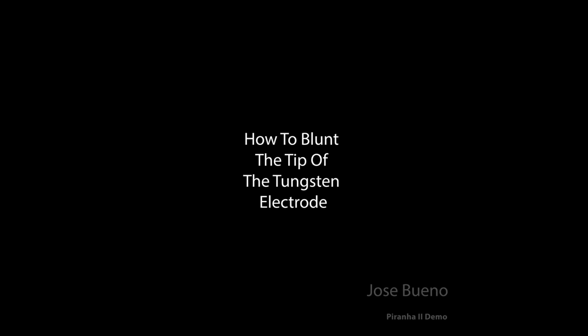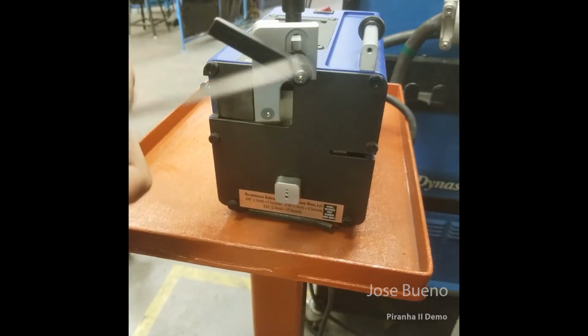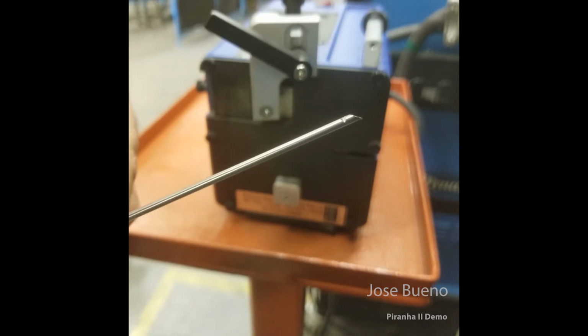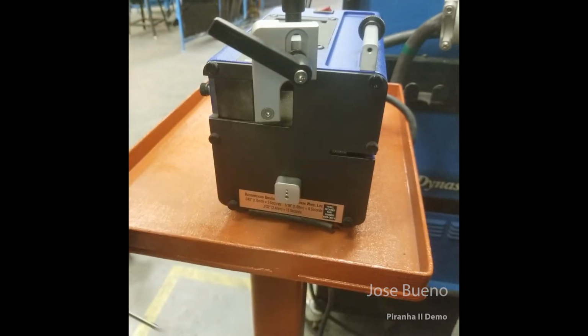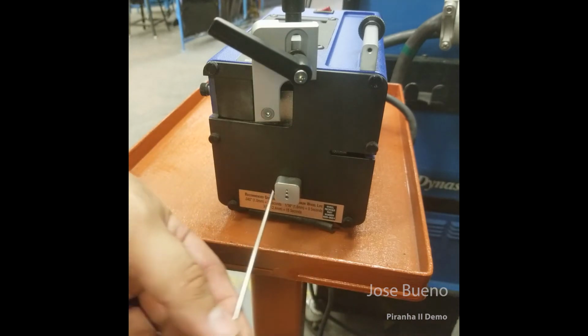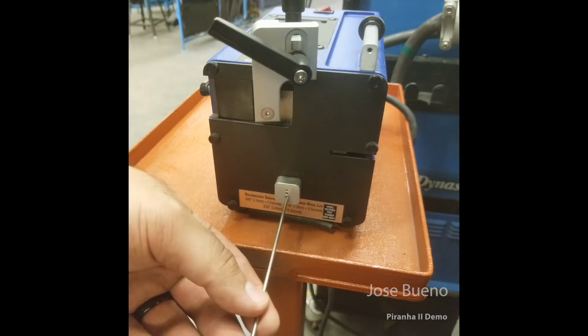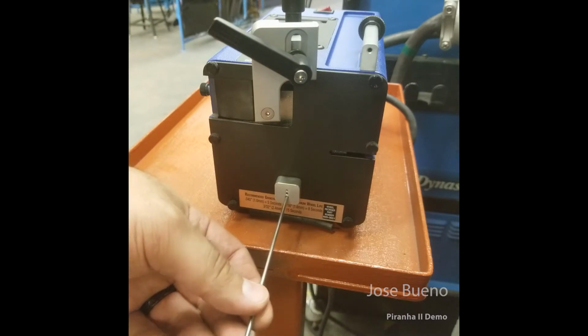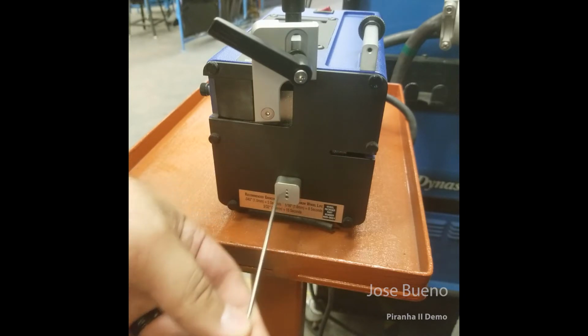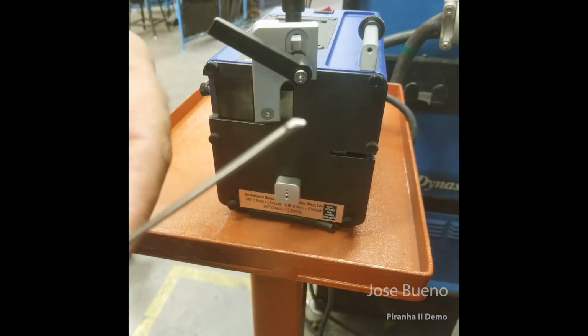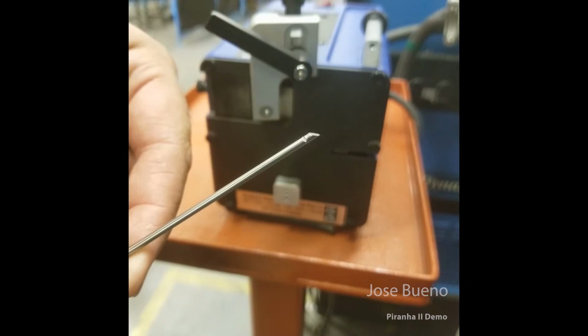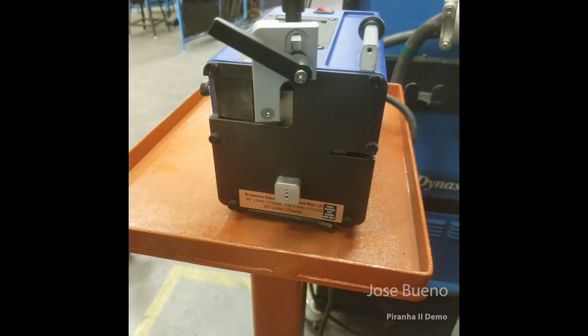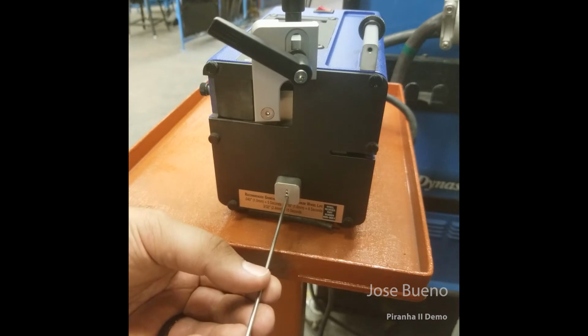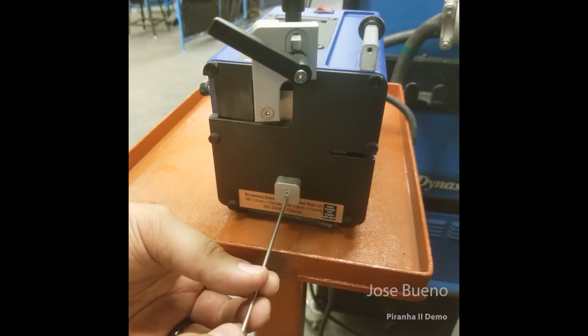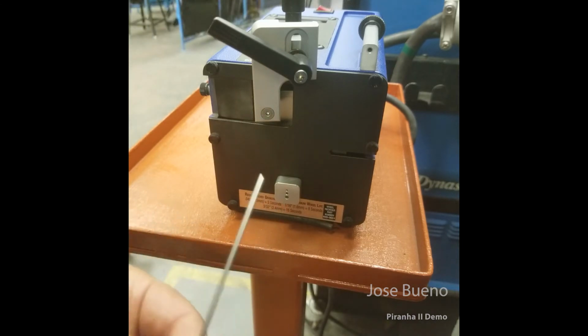Now that we've notched out our electrode and we've taken that contaminated portion off, it's time to blunt our tungsten electrode so that we can put a fresh taper on it. So what we're going to do is look at the bottom on the side of our Piranha 2, and we're going to see what looks just like the tungsten guide up towards the top where we can slide our tungsten and sharpen it, except the one on the bottom is to guide our tungsten to that grinding disc in order to blunt it. So as we insert the tungsten electrode, it's going to make contact with the grinding disc at a perpendicular angle, which is going to allow you to flatten the tip. It's important not to just shove the electrode in there, as you'll cause a groove to be worn into the disc. You want to just let the abrasive disc do the job.